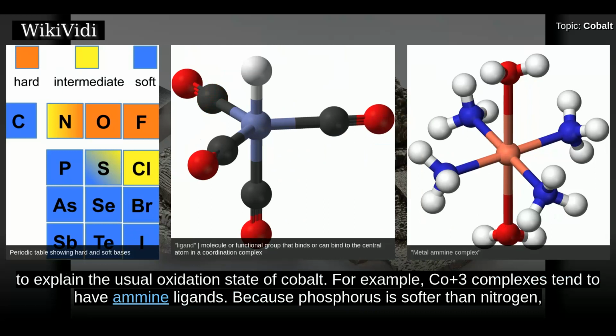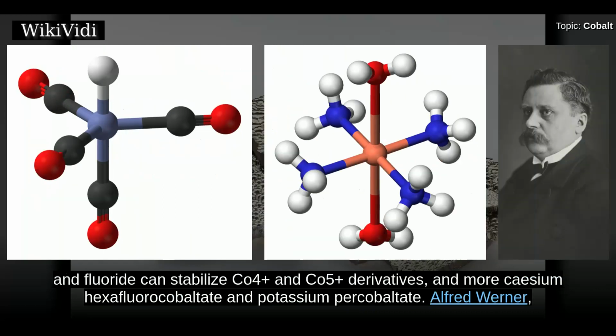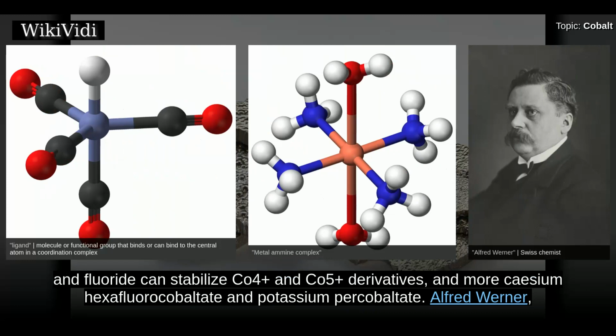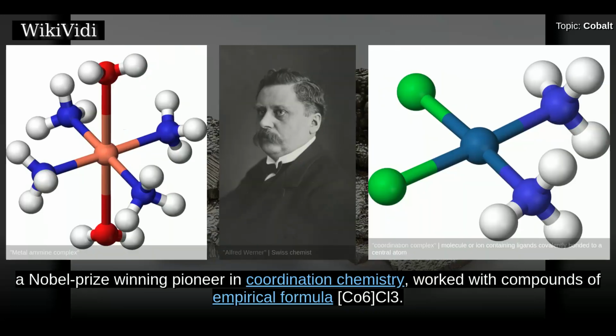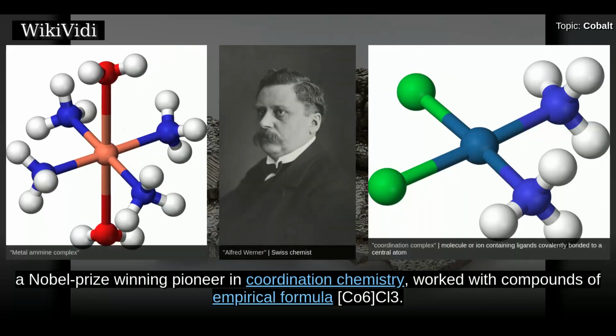Because phosphorus is softer than nitrogen, phosphine ligands tend to feature the softer Co2+ and Co+, an example being tris(triphenylphosphine)cobalt chloride. The more electronegative oxide and fluoride can stabilize Co4+ and Co5+ derivatives, as in cesium hexafluorocobaltate and potassium percobaltate. Alfred Werner, a Nobel Prize-winning pioneer in coordination chemistry, worked with compounds of empirical formula CoCl3 with six NH3.